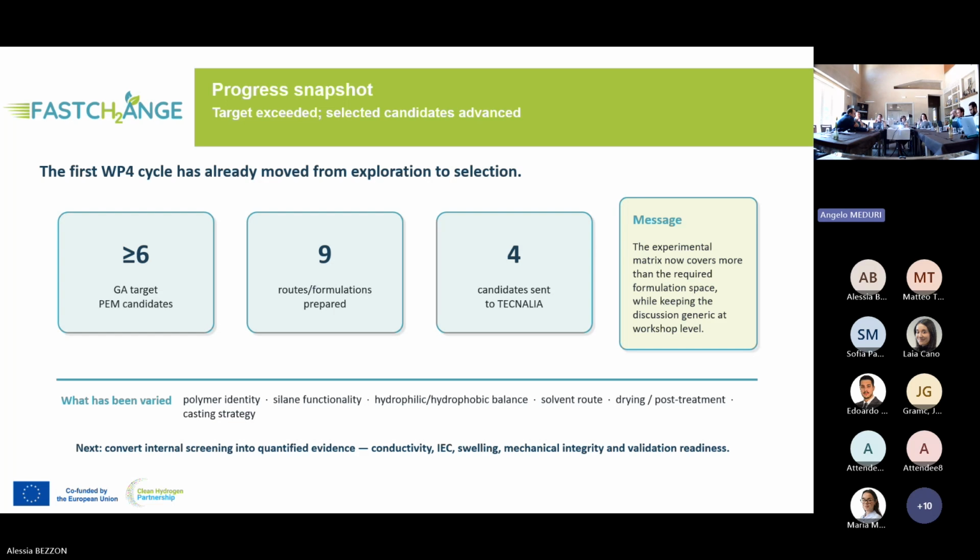The things that change between all these types of membranes are the polymers that we use as a backbone, the different functionalized silane, and the hydrophilic to hydrophobic balance. Also, we consider the different solvent route, different drying and post-treatment, and also casting strategies.